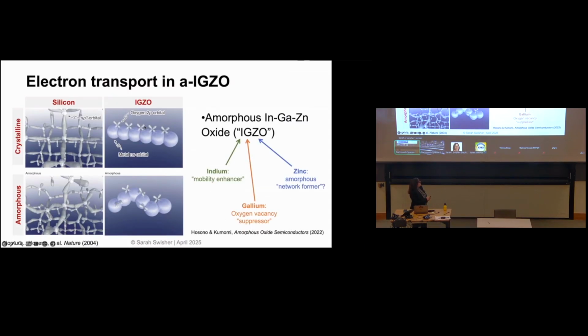So we typically mix these different metals, indium, gallium, and zinc, to make this oxide semiconductor. The different metals play different roles. I'm not going to go into that too much, but the material that we use primarily in my work is indium zinc oxide. So I mentioned that you can make these with a solution process, okay?